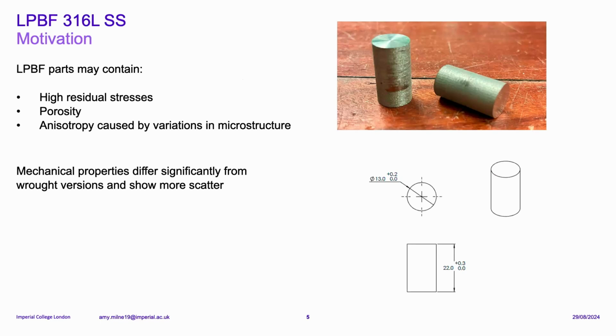At the minute, laser powder bed fusion parts may contain high residual stresses, porosity, and anisotropy, which can be caused by the variations in the microstructure. The mechanical properties have also been shown to differ quite significantly from raw material and show a lot more scatter.